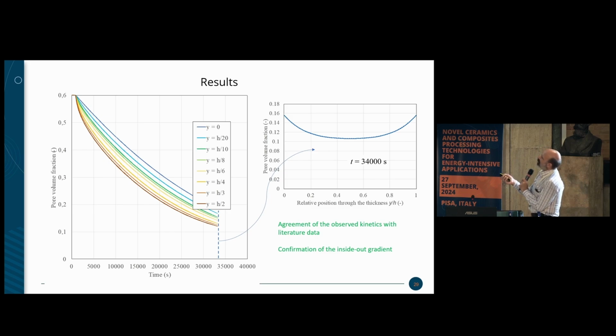So we have the value of porosity at selected points through the thickness. So this is the surface, and you see that the porosity at the surface diminishes, but slower than porosity in the middle, which is exactly what we want. And this is, for example, a final porosity profile here showing that indeed in that situation, with all the data that we had gathered from many steps before, we came to the point of having exactly the inside-out gradient. And surprise, using kinetics from literature, we found also agreement on the time scales, which was rather surprising, because in chemical kinetics, if you are 2 orders of magnitude away, you are sometimes very close to the result.